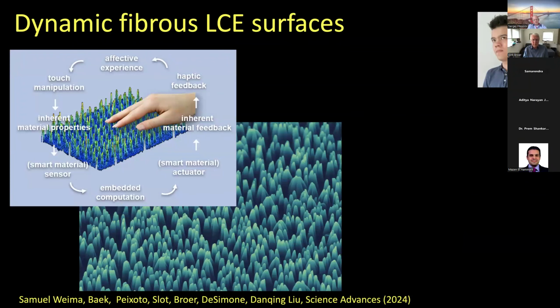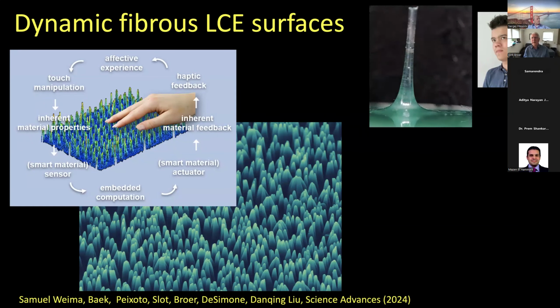I make another step because I want to finish with coming more and more to the soft robotics experience that we propose. You can also go to a surface where you have more or less fibrous structures. Also there you can use the liquid crystal elastomers. They have a viscosity such that you can easily draw fibers from the surface, and then just by actuating the fiber, you can actually modulate the orientation of the fiber.